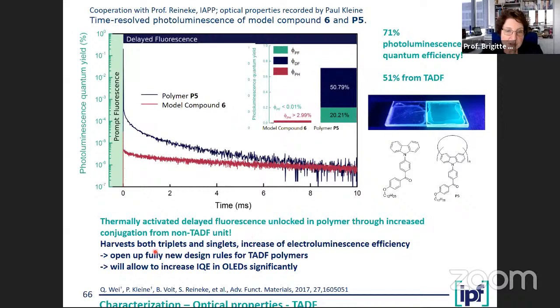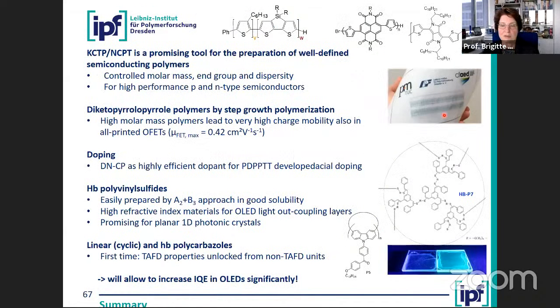And that was the base that we can actually do this by polymerization. So the monomer does not show this effect, but once we polymerize it to an oligomer at least, we get this beautiful, strong TADF emission. And that's also an important part and shows you the chemistry. So I think I should finish slowly.